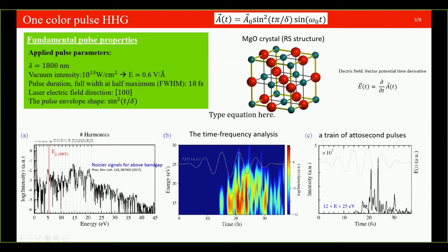the high harmonic generation is usually explained by interband and intraband contributions. For the first four harmonics here, where their energies are below the band gap, they arise from intraband dynamics, but for the higher energies, both interband and intraband contribute, and as a result of that, here we see a noisier signal.